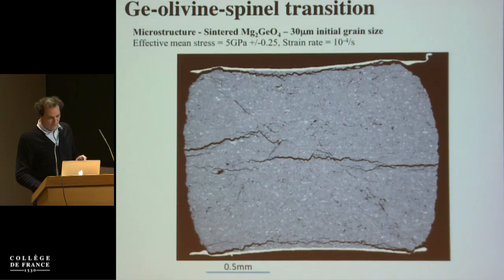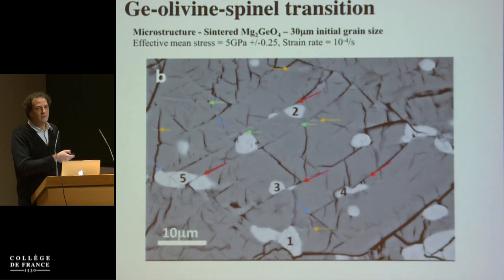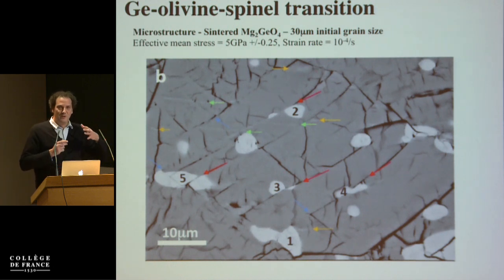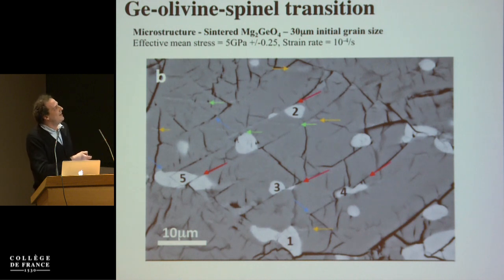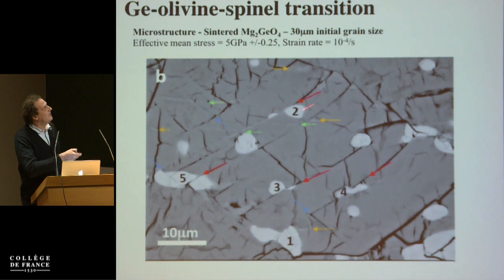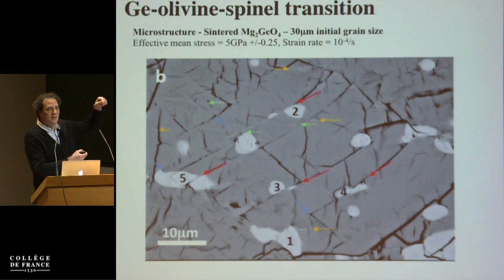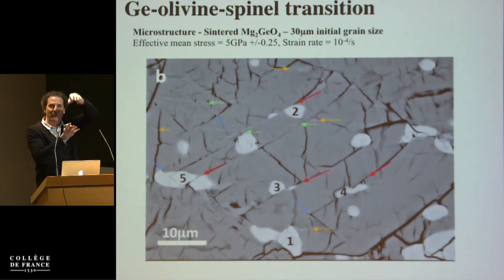So if you look at the sample now, I will show you just to finish a bit of microstructure. So this is the main fault. But before zooming on this main fault, we're going to zoom somewhere here. And this is a set of conjugate faults in the samples where you see small pyroxene grains being sheared. You can all see the sense of shear, etc. But our understanding is that those events that have large CLVD components might actually come not from a single fracture propagating in a single way, but by many fractures propagating together. So it's very hard to imagine, at least to me, that you had this fracture propagating, then this fracture propagating, then this fracture propagating. I would rather have an idea of all the fractures propagating together and the system collapsing a little bit like a deck of cards that you're pushing and all the cards moving together. And this could be the origin of the large CLVD component.